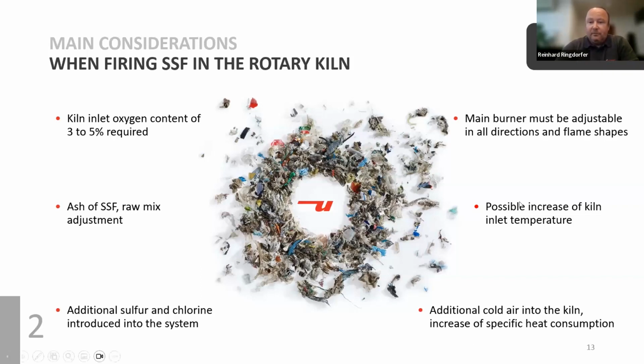We have a possible increase in the kiln inlet temperature, of course, because even if the fuel is very well prepared, it's not as well prepared as coal, for example, or petcoke. It takes a little bit more time to combust in the kiln, and therefore you will have a delay in the combustion. You will have a delay in the heat transfer to the clinker, and therefore a higher inlet temperature.